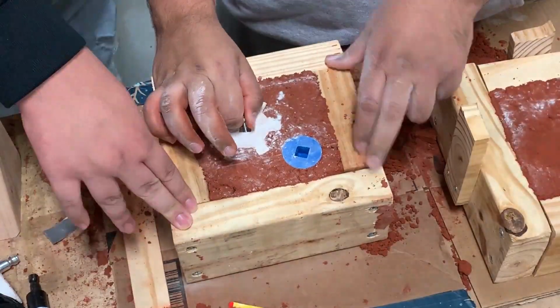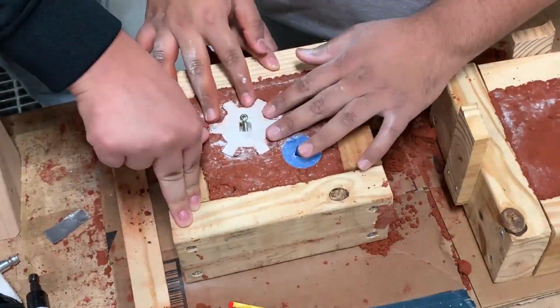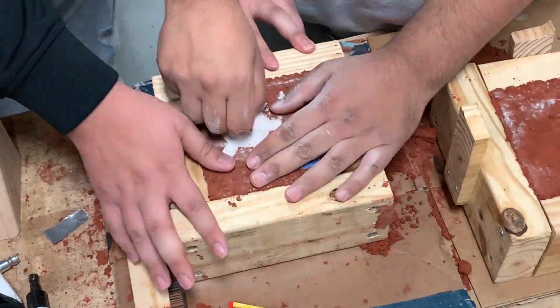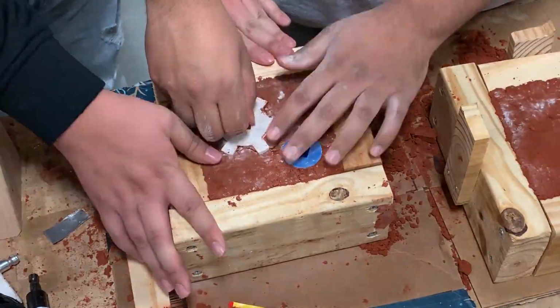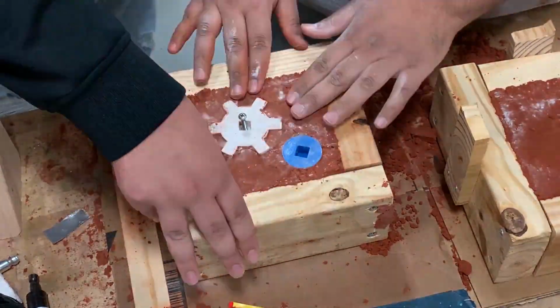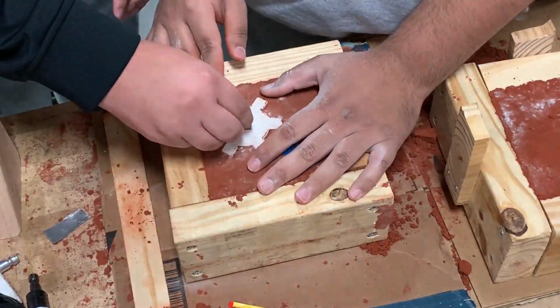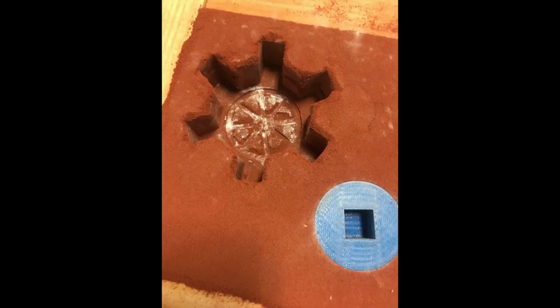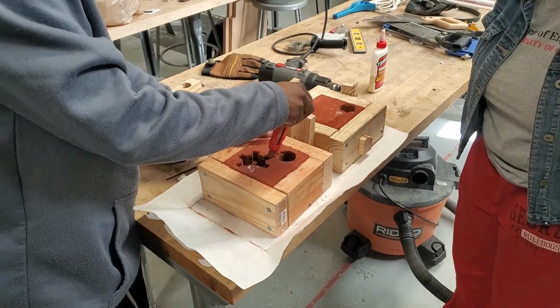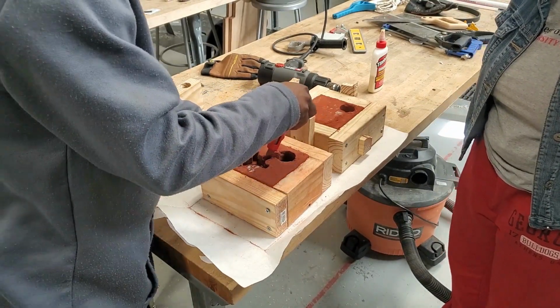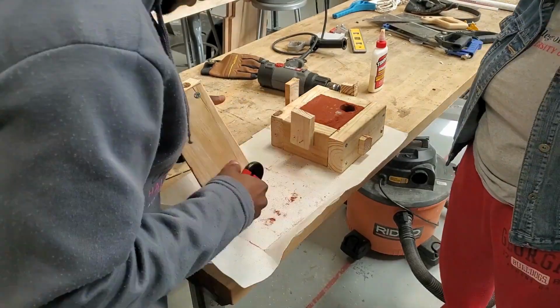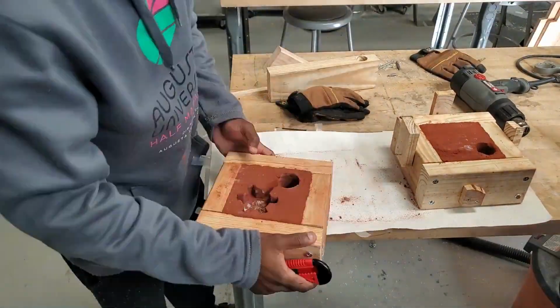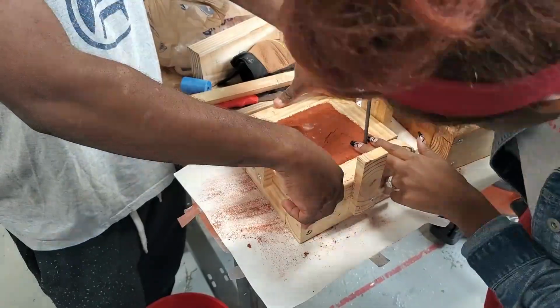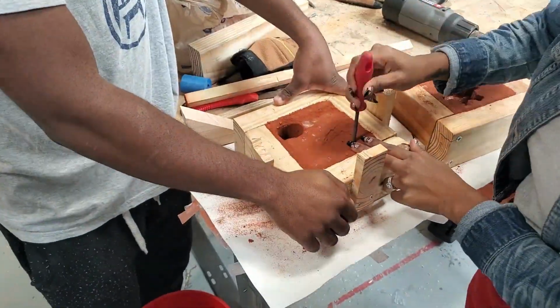We encountered one problem during this process. When we tried to pull our 3D printed pieces out of the sand, it would break the mold. After a few attempts, we figured out that the sand was getting stuck in between the layers of our 3D printed part. In order to combat this, we taped the sides of our 3D printed part and repacked the sand into our mold. After we fixed this problem, we made a path from our part to the sprue and poked ventilation holes into the cope. Now we were done with our mold and ready to melt our aluminum.